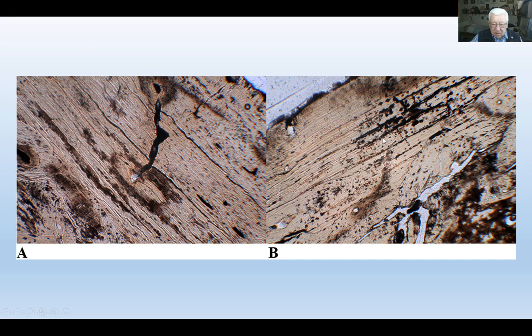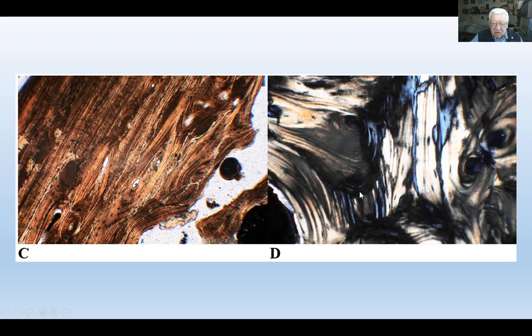Using polarizing light microscopy, the microscopic picture looks like this. There is cortex bone and you can see fissures — smaller and bigger — filled with clay migrating into the structure of the bone, between the fibers of collagen. This clay is migrating into the structure of the bone and causing mechanical destruction. Because clays consist mostly of kaolinite but there is a mixture of smectite — which is a swelling clay — and if there is water, the forces of swelling may destroy the structure of the bones.